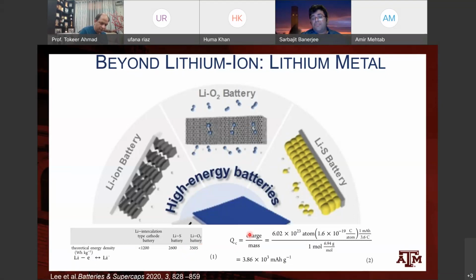Right? So if you calculate for lithium metal, charge divided by mass, so Avogadro's number times charge 1.6 × 10⁻¹⁹ divided by the atomic mass of lithium, you get the capacity to 3.86 × 10³ mAh g⁻¹.